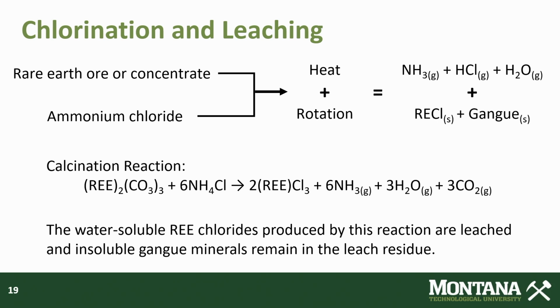Put that in a reactor, add some heat, rotate the reactor to get good solid-to-solid contact. And what happens is we're going to produce the rare earth chlorides. We'll have some gangue constituents present. And then, of course, we're going to have an off-gas that's going to contain appreciable quantities of ammonia because of the excess ammonium chloride that we add, and also ammonia is not consumed in the reaction itself. It's just released as a byproduct. Some hydrochloric acid gas, H2O, and then also some carbon dioxide is shown in the reaction below.